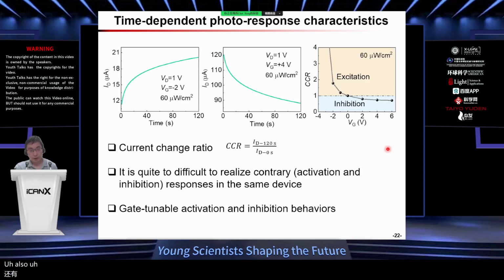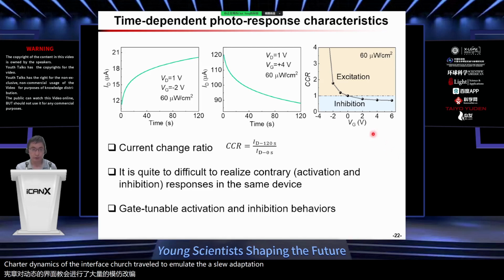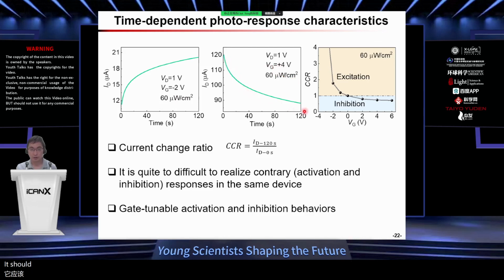Also, we can use gate voltage to do the fast adaptation, but we can also use the charge dynamics of the interface charge trap to emulate the slow adaptation process. Here you can see, if the light intensity is constant, with continuous illumination on top of the phototransistor, and then we apply a negative gate voltage, you can see the photocurrent keep increasing. It shows the activation behavior. But under the same lighting condition, with continuous lighting, if we apply a positive gate voltage, it shows the inhibition behavior.